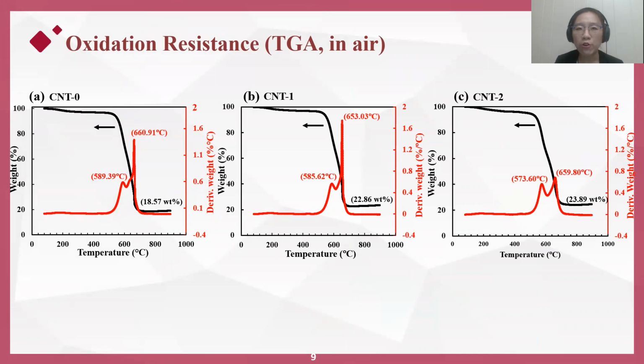One of the most basic characterizations to assess the CNT quality is thermogravimetric analysis, TGA. Here we're comparing the as-produced CNT from both the control group and the water-containing systems. With increasing water concentration, the first derivative weight peak, shown in red, was observed to shift to a lower temperature, from 589 all the way to 574 Celsius, indicating an increasing amount of higher curvature, possibly smaller diameter CNTs, because of their higher reactivity with oxygen.